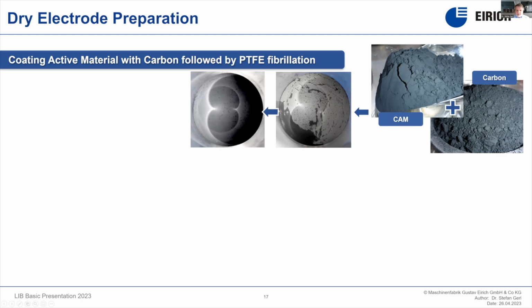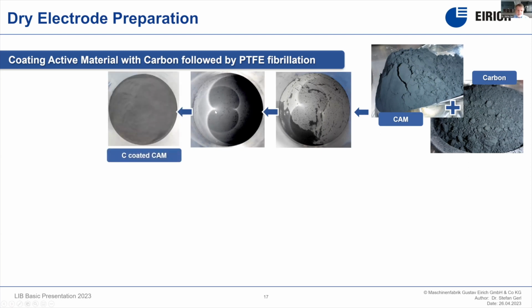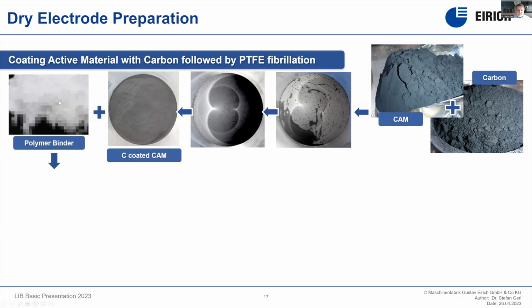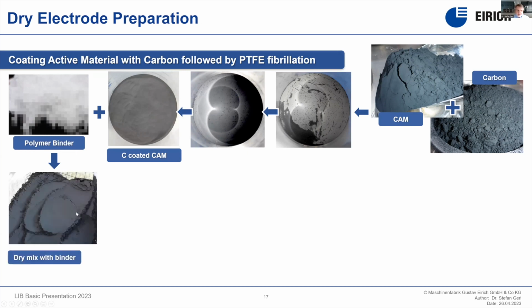And if we, let's say, go on with the mixing time or increase the mixing speed, then after a certain period of time, which is significantly longer than the time for just pre-mixing in the wet application, we have a fully coated active material. And then we add the polymer binder, which is typically a PTFE. We mix this in. So at the end of this first step, we have a, let's say, homogeneous powder mix, which can be applied for a dry application already. When you're, let's say, hot rolling it directly onto the collector foil.